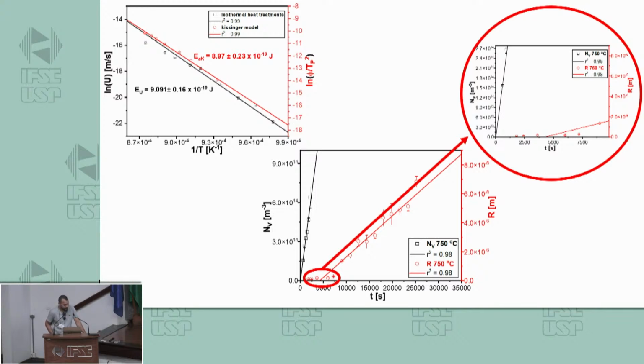isothermal and non-isothermal heat treatments can be used to measure the activation energy. In this case, a non-isothermal method is used, the DSC method, and the Kissinger equation is used to demonstrate that the same activation energy can be measured, as we can see here. For more details, we invite everyone to see our poster. Thanks for your kind attention.